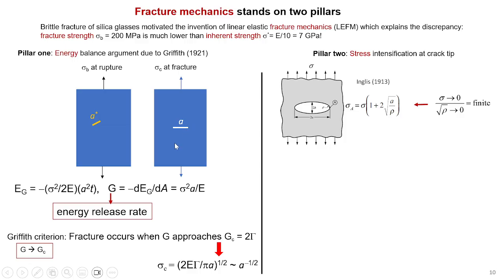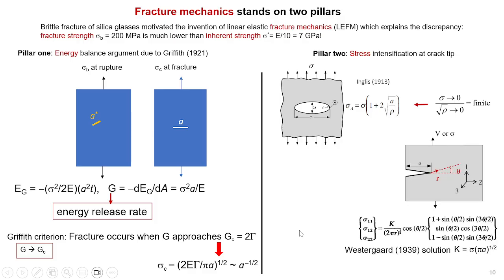So he worked out an energy argument to indicate that it happens when the so-called energy release rate is higher than surface tension. And there's more work on this side later on, in '39, when you consider a very sharp crack, you also find that the stress diverges as 1 over square root of r. So as you approach the tip, it goes to infinity. And what regulates the strength is the so-called K, which depends on the so-called far-field load. So these are all simple mathematical results. What bothers them is the divergence.